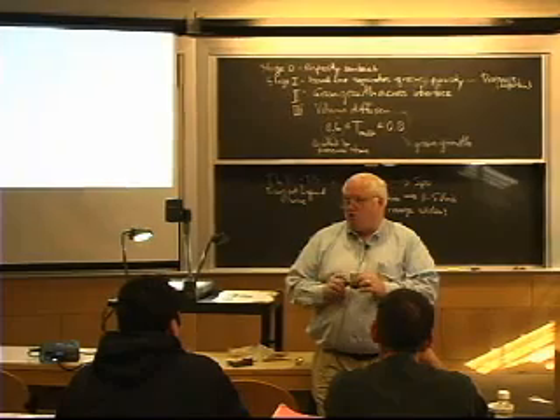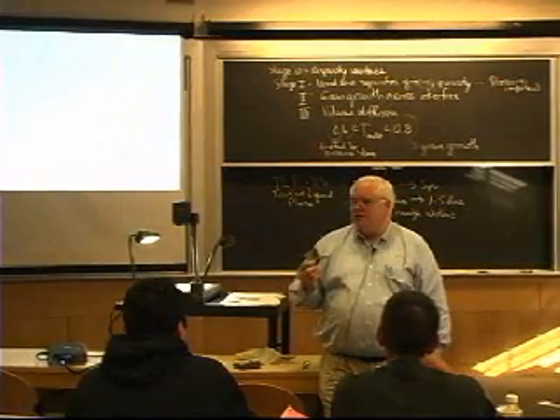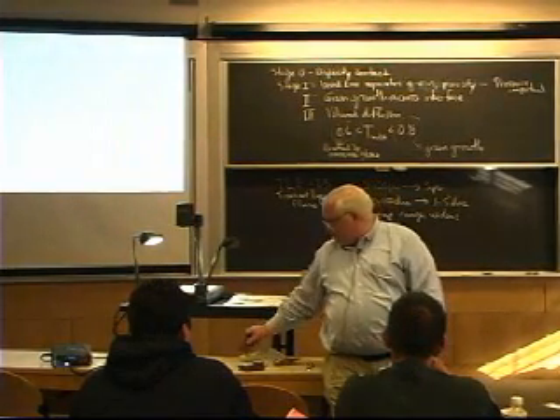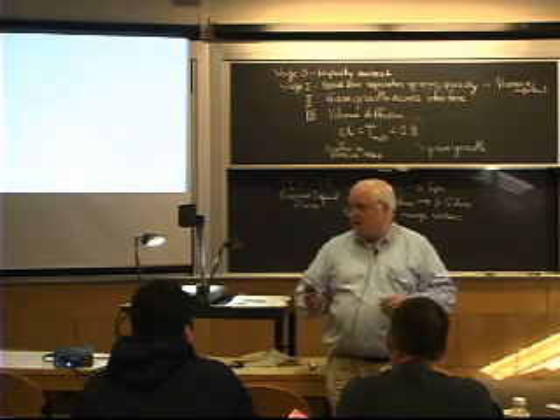See the crack? Pretty good sized crack. This one happens to be too big to repair, but you can repair cracks in these things depending on the alloy. This is a nickel-based alloy. You could repair that maybe if it was a quarter inch in size, but you can't repair it when it's 5/8 of an inch in size. But you can repair it and put it in service for another 3,000 hours.